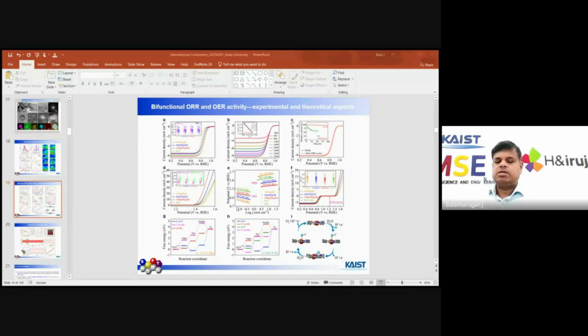So after that, the kinetics may be further proved by the Tafel plots. You can see the Tafel value. The Tafel value is very small, which means higher kinetics towards ORR as well as OER. When compared to the other catalyst, maybe lower Tafel value, because the lower the value, the better it is for ORR and OER. And this is the real performance for ORR and OER. And close to ORR OER, because the distance between these is very close, that may be called a better catalyst compared to the other catalyst.